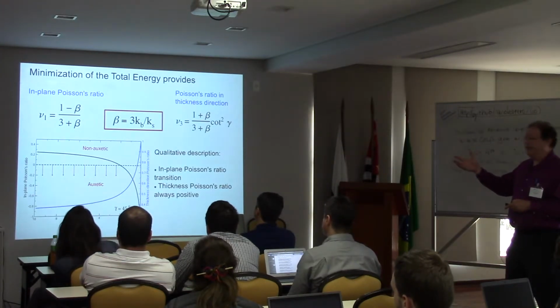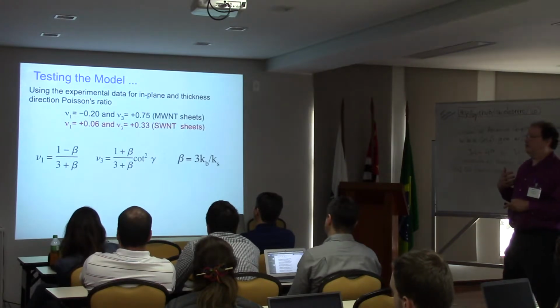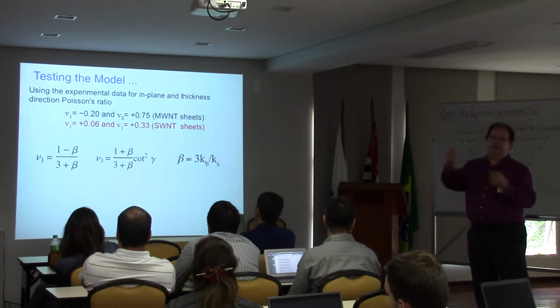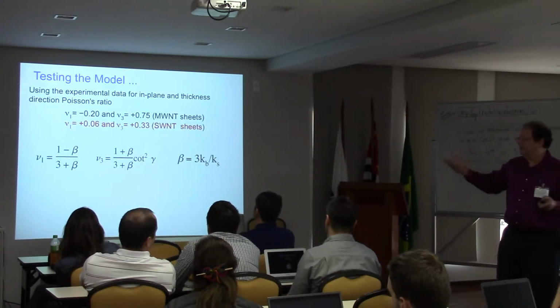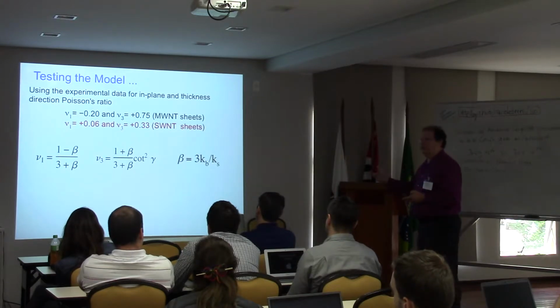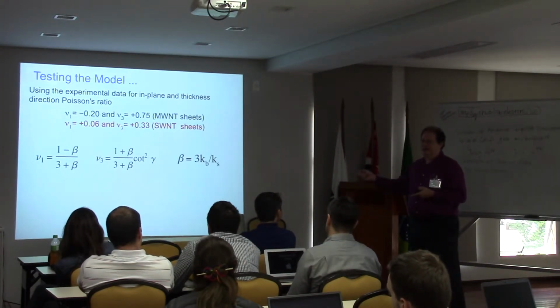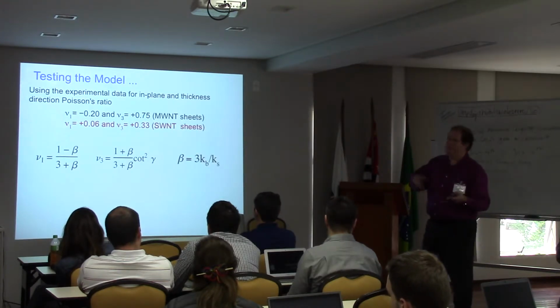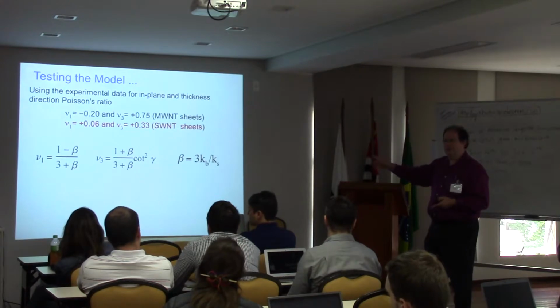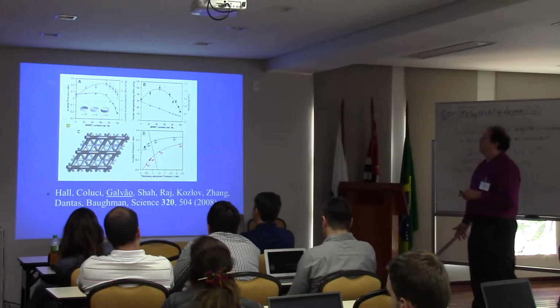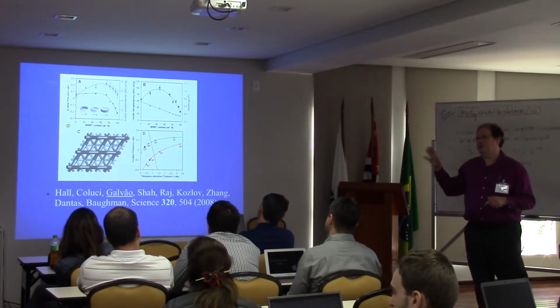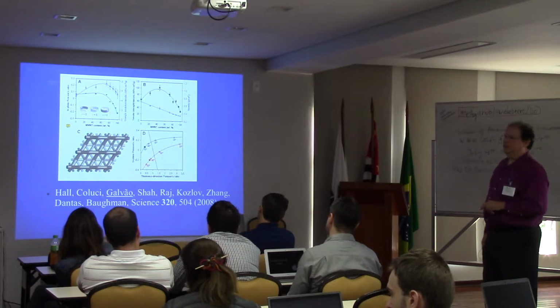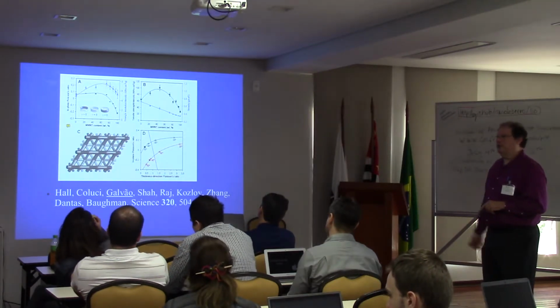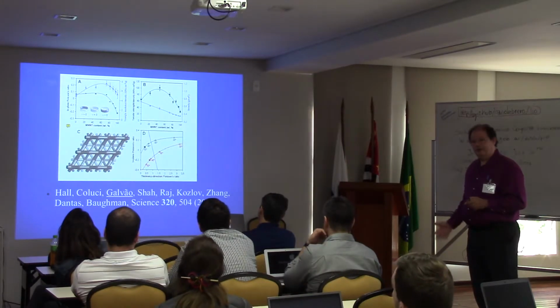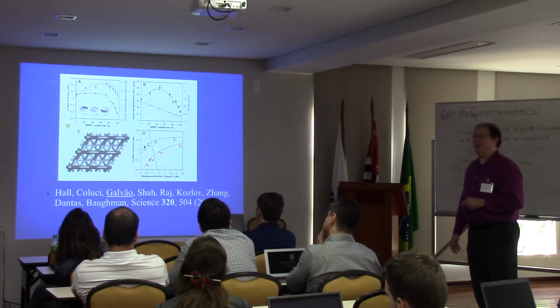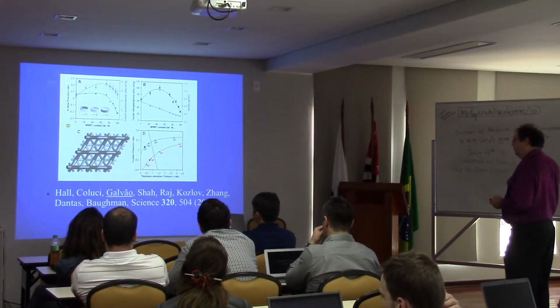It passed the crucial test. And most important, I can derive expressions that give numbers that can be directly compared against the experimental data. So we can help the experimentalists improve the behavior. What should they do? They should increase density, they should decrease density, they should increase the length, they should decrease the length. We have a model that predicts the behavior if you do exactly this. And when you compare the data, it's amazing that we could create a model that fits the experimental data quite well. Again, it proves that you can create a model that is very simple, but still complex enough to capture the major features of the behavior.